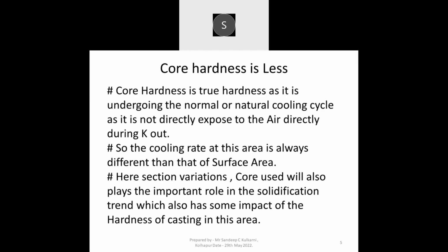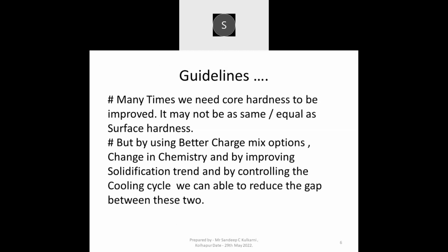Core hardness is less. Core hardness is a true hardness as it is undergoing the normal or natural cooling cycle, as it is not directly exposed to the air after or during knockout. So the cooling rate in this area is always different from that of the casting surface area. Here, the section variations and the core used also play an important role in the solidification trend, which also has some impact on the hardness of the casting in the core area. But even after that, the hardness in the core area will always be lesser than that of the surface hardness.